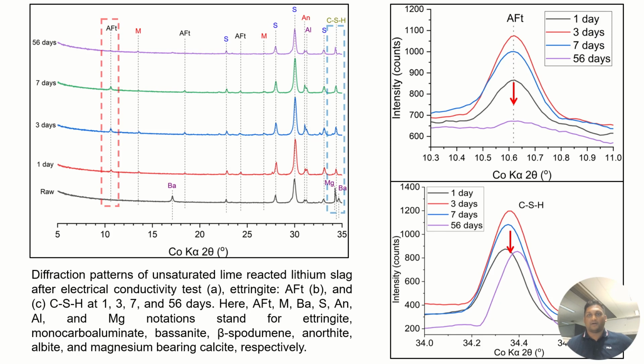The diffraction peaks of the lime reacted lithium slag at 1, 3, 7, and 56 days were analyzed for the crystalline phases of the hydration product, shown in left. Here the ionic phases were determined in the cobalt K alpha radiation, and the formation of ettringite and calcium silicate hydrate at 10.61 and 34.15 were analyzed as shown in right. The formation of the ettringite and calcium silicate hydrate degrade with time as the reactive light metals may incorporate to form amorphous and amorphous intermediate hydration products.